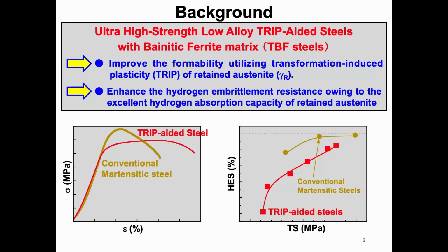In ultra-high strength low-alloy TRIP-aided steels with bainitic ferrite matrix, TBF steels, it has been reported that TBF steel possesses high strength and excellent ductility and press formability owing to the transformation-induced plasticity of retained austenite. And TBF steel enhances the hydrogen embrittlement resistance because of the high hydrogen absorption capacity of retained austenite.